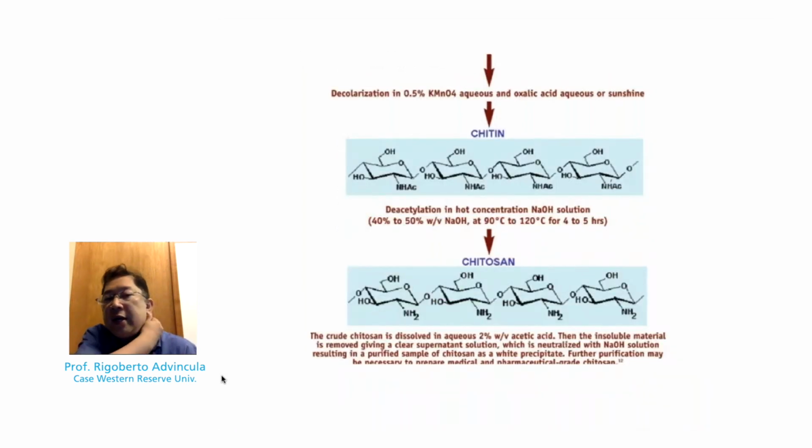So as you can see here, the chitin that is isolated and with the removal of the protein with the sodium hydroxide solution has to be then neutralized by the addition of acid. So it's the chitosan, which is deacetylated, which is considered the more processable form of the polymer. And this is what you'd find in many applications, including biocompatible surgical applications and implants as well, not only